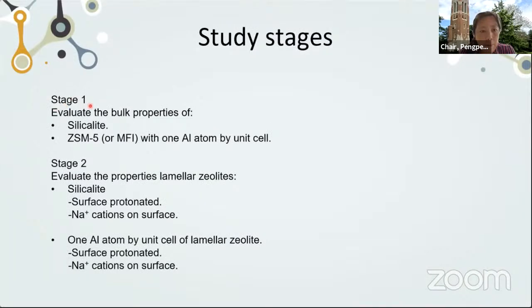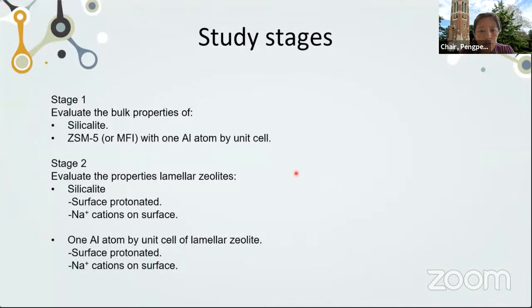For stage 1, we evaluate the bulk properties of silicalite and ZSM-5, or MFI, with 1 aluminum atom per unit cell. Here, silicalite refers to the ZSM-5 zeolite framework composed only of silica. In stage 2, we evaluate this bulk zeolite, but in laminar configuration. Since in the model of laminar zeolite the surface has oxygen atoms with 3 bonds, in our study we considered both the case where the 3 bonds on the surface are saturated with protons or sodium cations.